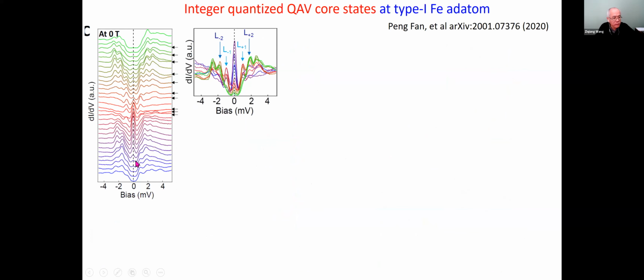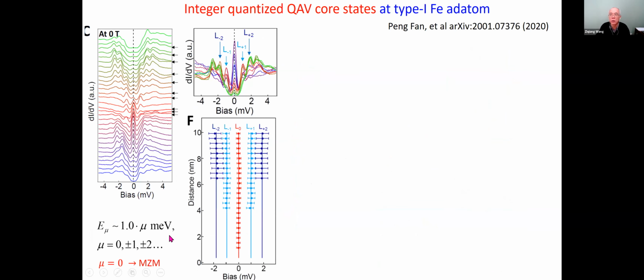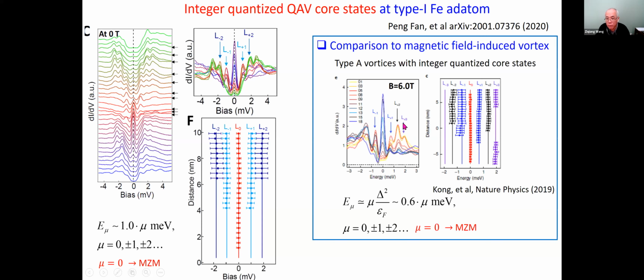Now, this sample is always inhomogeneous. So the trick is to collapse all of these waterfall plots onto a single plot. You see, in addition to a zero energy bound state, you see also other states. And if you look at these states, they are integer quantized. In fact, it's about 1 millivolt times an integer, including 0. So this is really concrete, I would say, one more evidence that indeed the ion induced a vortex, because you see the vortex states. And you compare this to a magnetic field induced vortex, where also these vortex core states are seen. And that's 0.6 times the integer. So you really just increase the mini gap of the vortex state by a factor of 2. And they're completely analogous to one another.